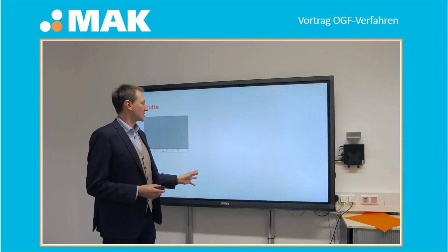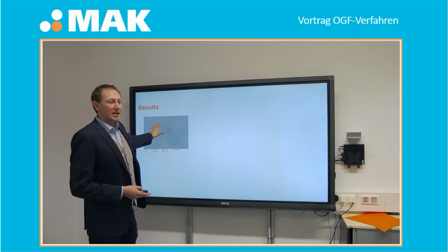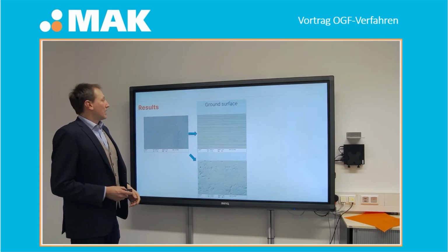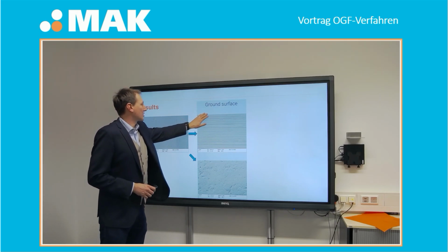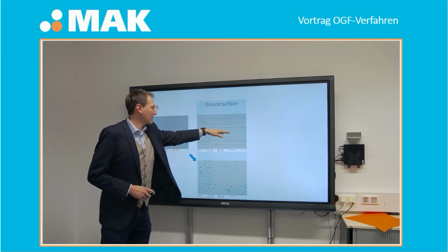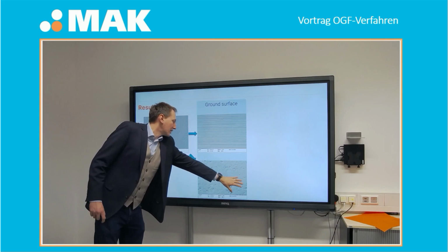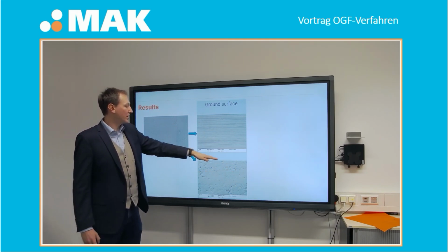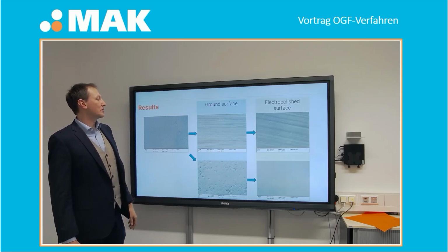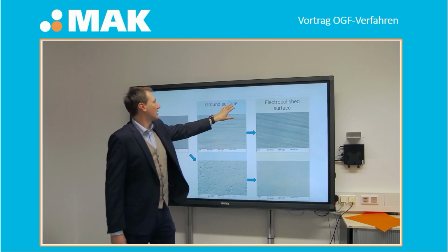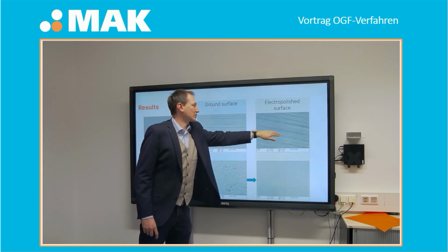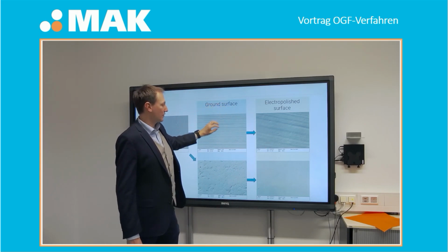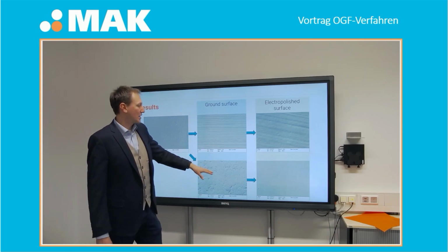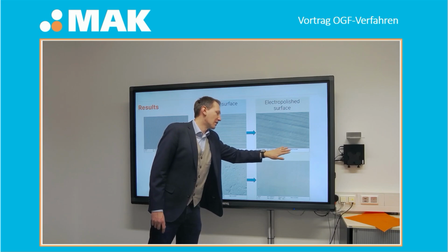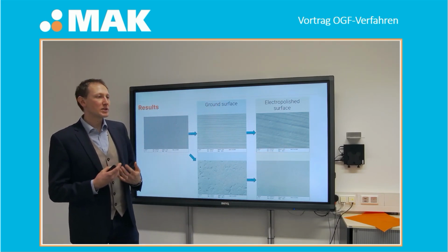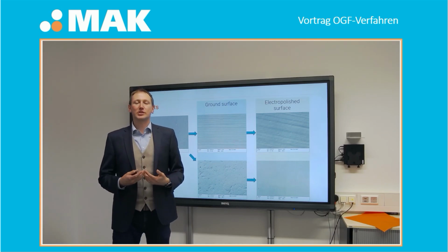Okay, and how does a surface look? Well, starting with a standard surface of stainless steel you get from your steel supplier. If you do a normal grinding process, a ground surface like shown here, you have this linear structure from the grinding. If you do this optimized grinding finish, you see that you have a homogeneous structure, no linear structures left on the surface. If you do electropolishing afterwards, you can see even after electropolishing linear structures on the surface left by a standard ground surface. But if you do OGF first and then electropolishing afterwards, you have a very homogeneous surface with no visible structures left.